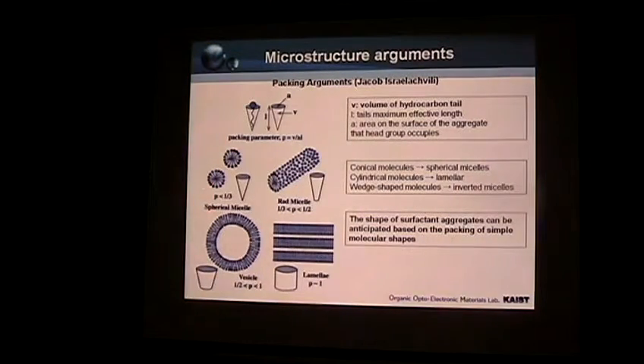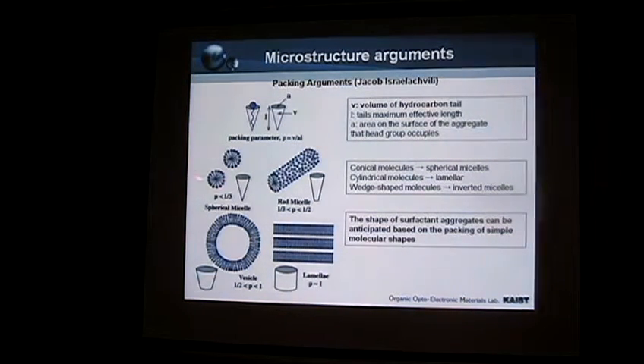And when the packing parameter P is less than 1/3, it usually forms spherical micelles. Okay, when it is in between, that forms rod-like micelles, also called worm-like micelles, cylindrical micelles; rod micelle is the same. And when the packing parameter is between 0.5 and 1, it forms a vesicle phase. The vesicle phase is close to the bilayer. And when the packing parameter is 1, it forms lamella. Same as in a block copolymer system. Okay, so the packing parameter determines these kinds of structures.